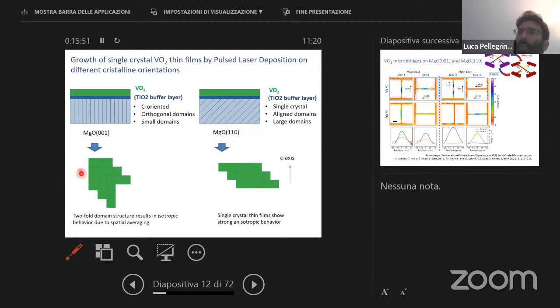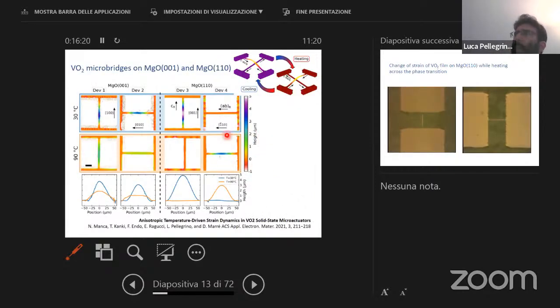If we grow on the 001 substrate, we have isotropic behavior, because the films grow with the c-axis in the plane, but we have two orthogonal domains. Instead, if we grow on MgO 110, the c-axis is in the plane, but the films are oriented as a single crystal. So we have some anisotropic behavior, which is clearly demonstrated by the next slide,